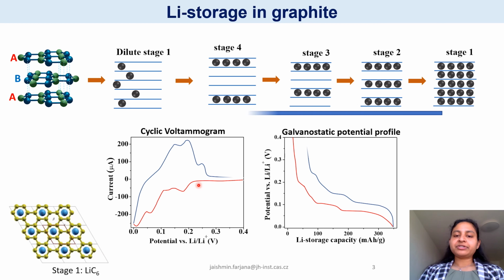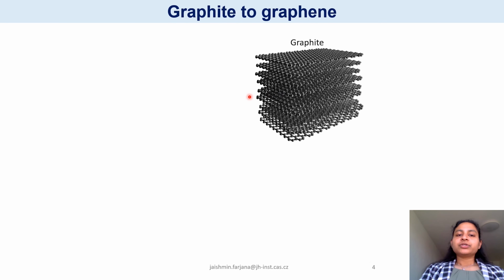When we discharge the battery, the lithium comes out from the graphite structure and a reverse peak in the cyclic voltammetry or plateau in the galvanostatic potential profile appears. So graphite is a very good material for lithium storage. It is very stable for multiple cycles of lithium going in and coming out.